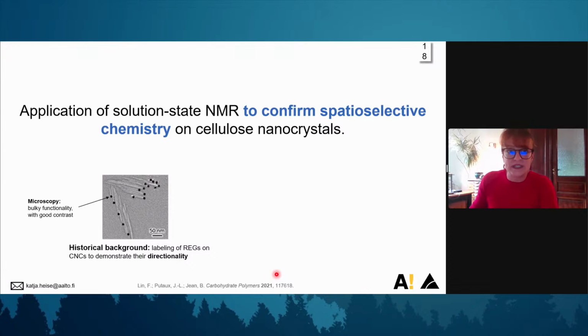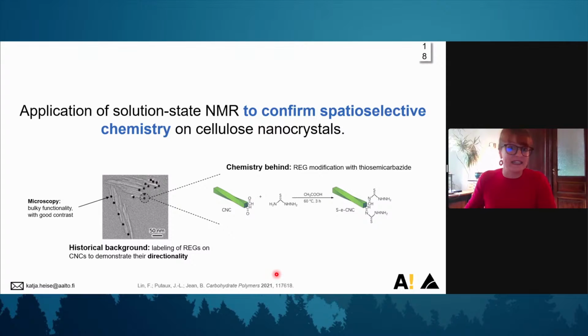What they used is a silver labeling approach to be able to use microscopy. For microscopy, you of course need a bulky functionality to attach to the reducing end with a very good contrast. What I'm much more interested in is the chemistry behind it. For the silver labeling approach, they use a thiosemicarbazide to attach it to the reducing end groups. And I'm much more interested now in the molecular information that is necessary for that, and really the modification of the cellulose.